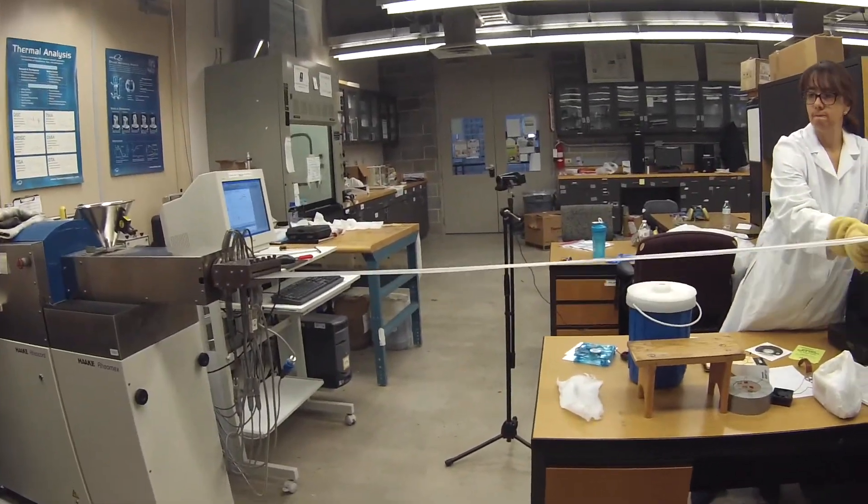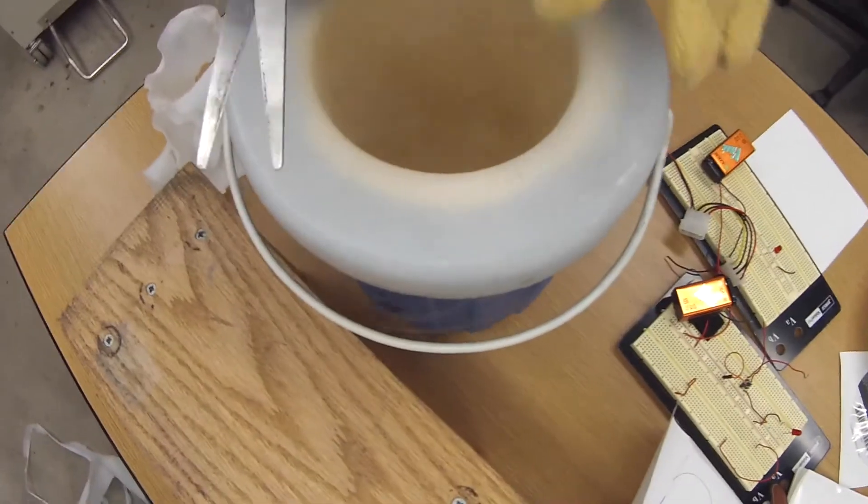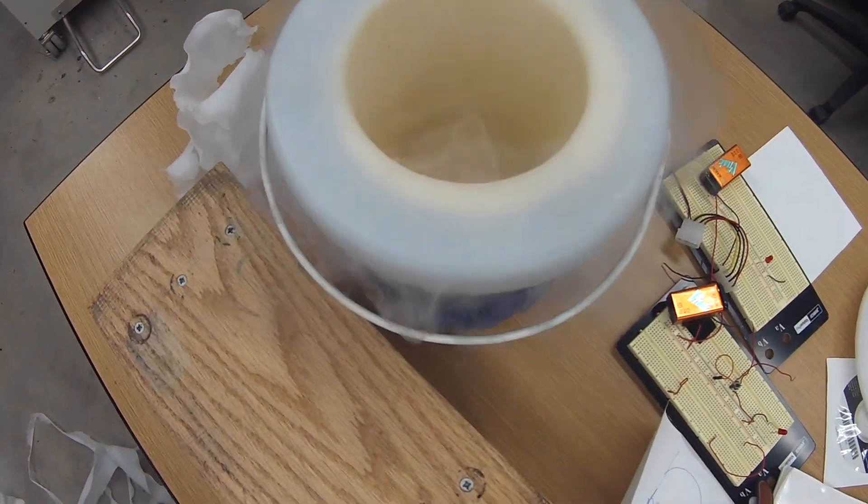I'm having some fun here preparing a thin film manually. Oops. Let's try to quench a piece of this amorphous material. I am placing it in liquid nitrogen, therefore cooling it really fast and freezing it to retain the amorphous properties.